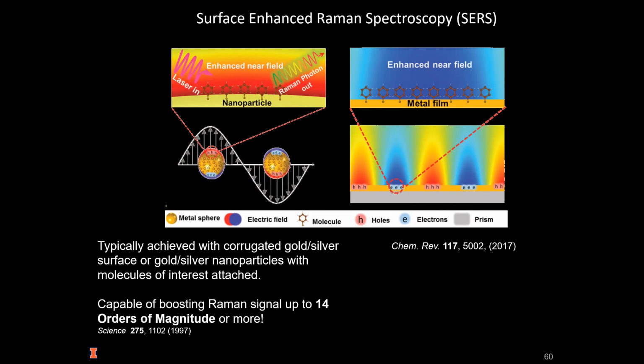But the question is more about surface—do you need to prepare the surface to have it smoother before certain measurements, or are some techniques more tolerant to surface roughness or damage? Most optical measurements are very tolerant of surface roughness, so you don't need any special preparation there. When you go for ellipsometry, you need a basically mirror-like surface, otherwise you don't get the specular reflection needed for the technique to work.